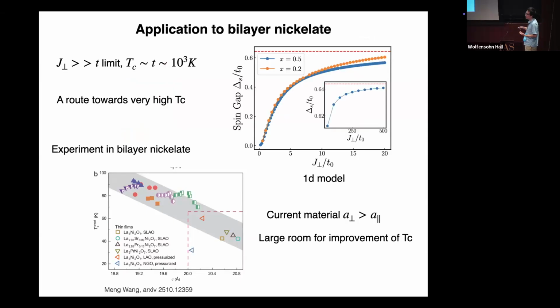So this is some data from the experiments so far. In this bilayer nickelate, they have many compounds, so they can show how Tc depends on the z-axis lattice constant. So you can find when you compress the bilayer, make the z-axis lattice constant smaller, Tc actually goes up. So this suggests maybe you increase J-perp and the Tc goes up. And so far the change is small, it's just 10%, but the Tc already increased from 40 to 100.